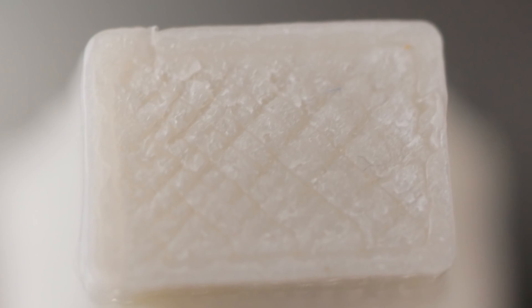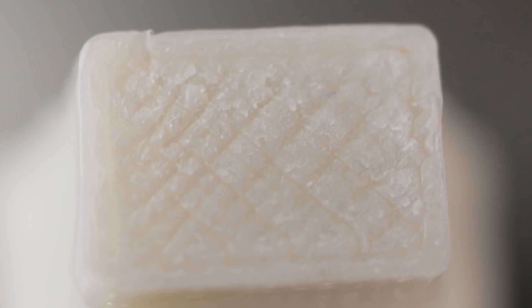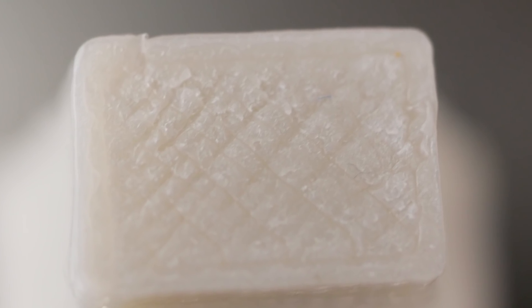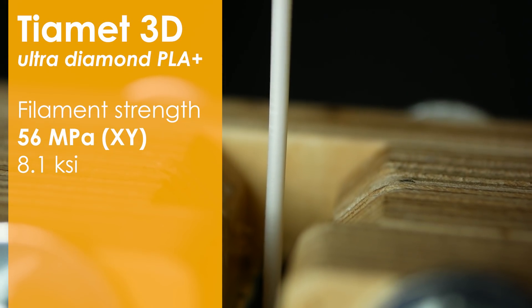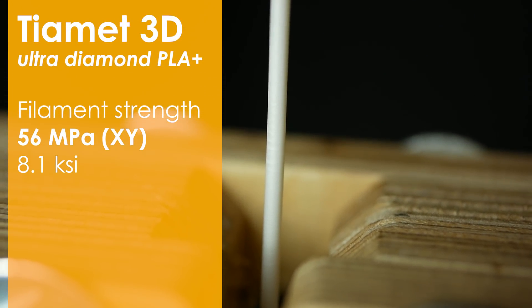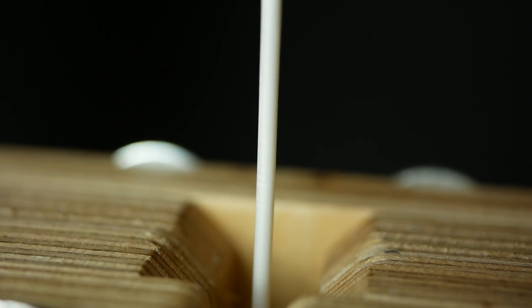I don't know if this is the normal composite problem or if the base resin they used with fast crystallization is the reason the layers don't bind very well. The material doesn't seem to degenerate during printing because also the filament strength test showed an ultimate tensile strength of 56 MPa.